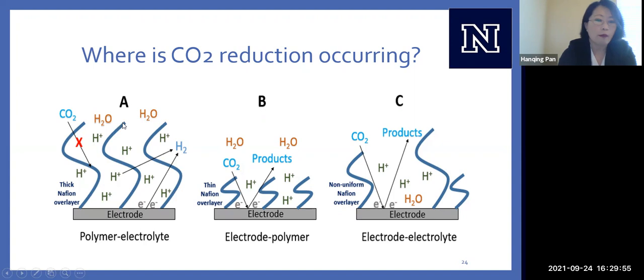At the polymer is represented by these blue squiggly lines. Polymer electrolyte, so electrolyte is our solution. Polymer electrolyte interface up here on top. If we have a thin enough Nafion overlayer, everything can diffuse through. So our CO2 is easily diffusing through that thin layer of Nafion, and it's getting reduced on the electrode surface, generating products. And at the same time, we're also seeing hydrogen being generated. And now the reaction is happening down here at the electrode polymer interface, so right here.